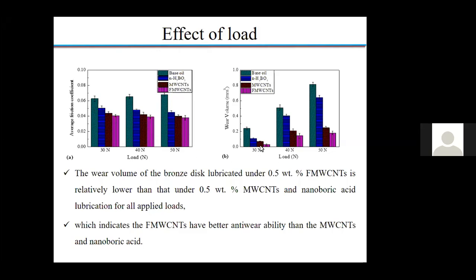The same thing is happening with respect to increasing load, and there is a significant reduction in wear volume with respect to increase in load. So both the friction and wear parameters were minimized by using these functionalized multi-wall carbon nanotubes. So that is the beauty of this functionalization.